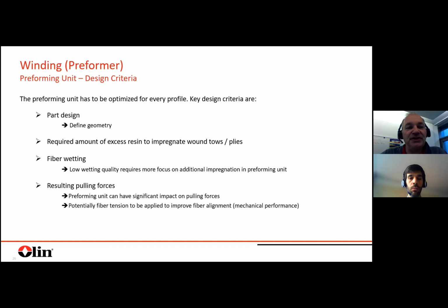But there's also a potential need to extend a little bit the functionality of the preformer. So if you have, let's say, a bit more challenging fiber, which needs higher viscosity systems, you need to force the resin more into the fiber. So that means that you have to extend or integrate a kind of impregnation step. So for example, just a few deflection bars on the way of the roving from the bath to the forming station to further improve the impregnation in the tows. Really to be validated what is required, and it depends for sure on fiber and resin.